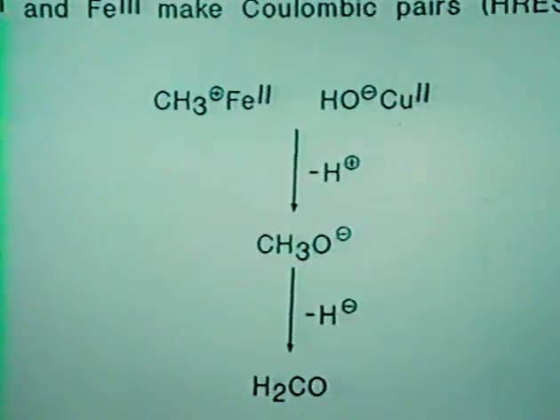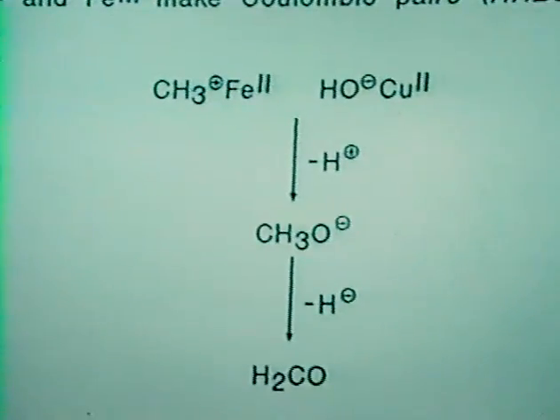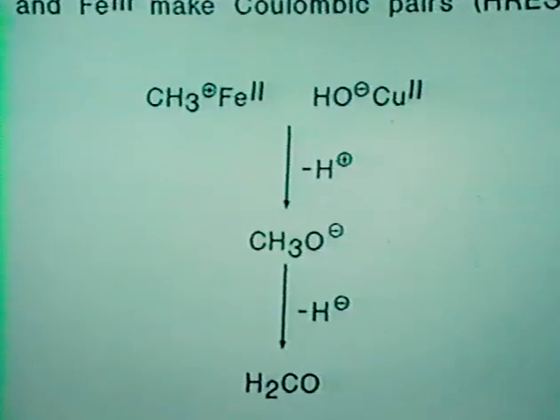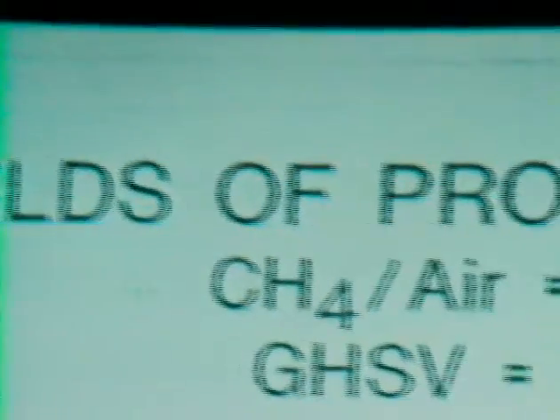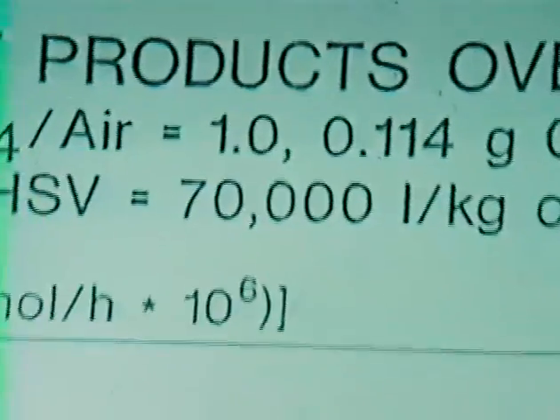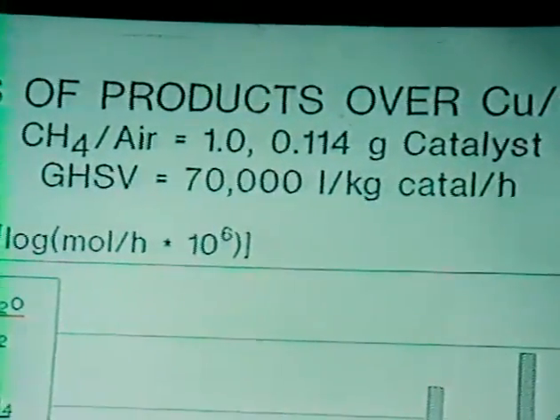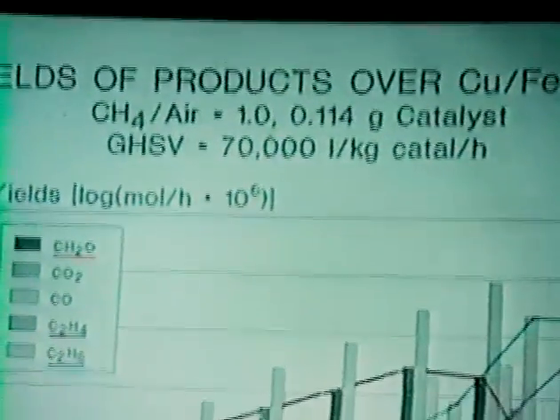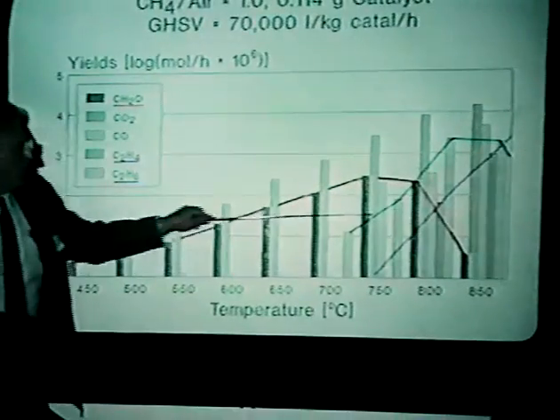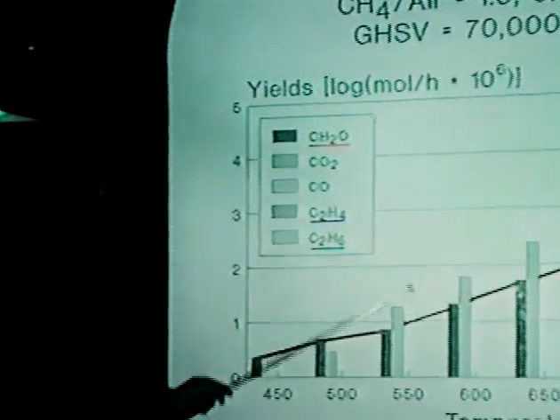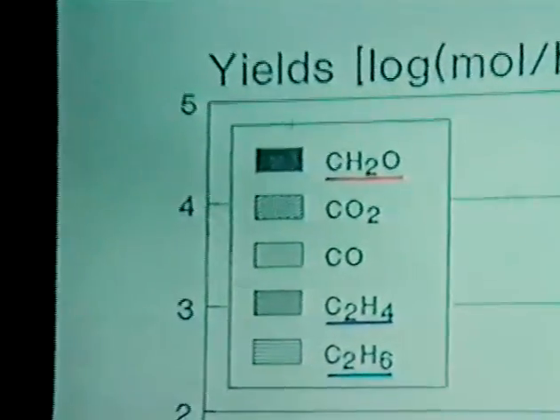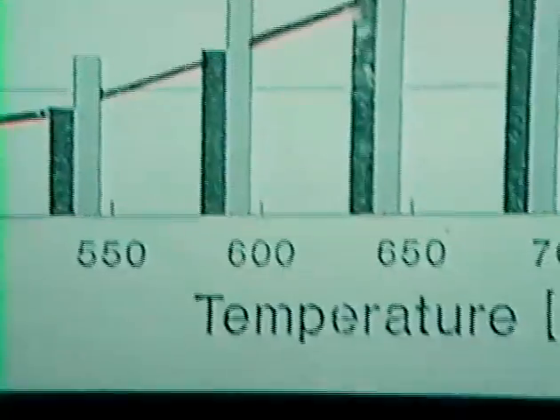And this is just about to appear in ChemComms. Of course, ChemComms are only accepting the results, not the mechanistic arguments. What is actually appearing there is the selectivity switch. We initially have the zinc oxide, which produces the C2 hydrocarbons. By the time we have doped the zinc oxide with the copper and iron, we are making formaldehyde at temperatures that are lower than those for C2 hydrocarbons, and that formaldehyde chemistry simply takes over. And this is all at fairly low pressures.